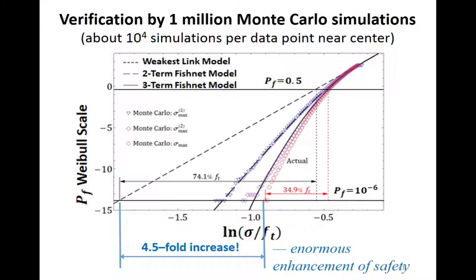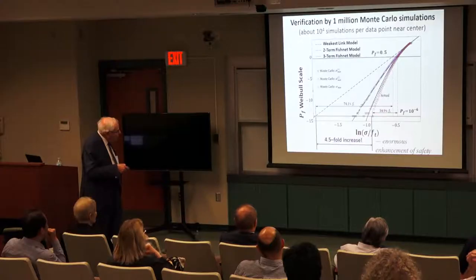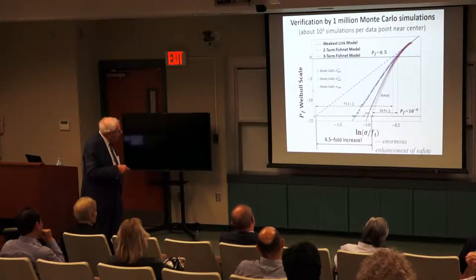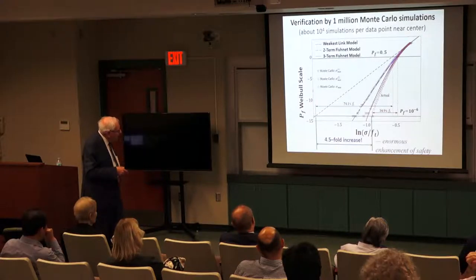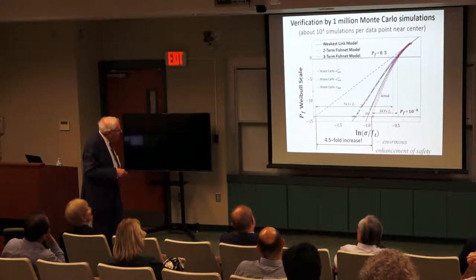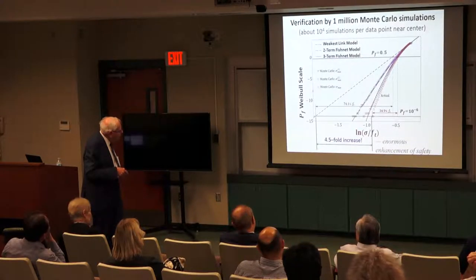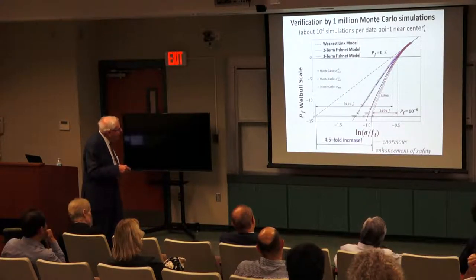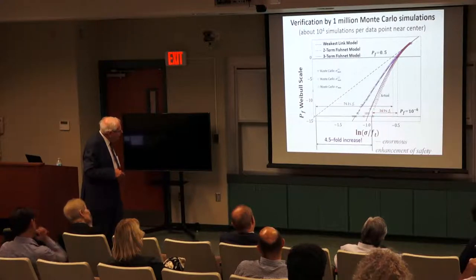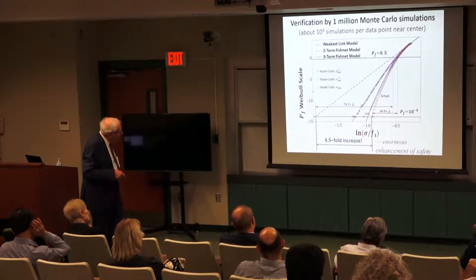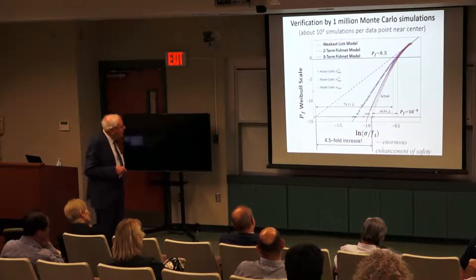This is again the line of 10⁻⁶, and you see the enormous saving. So if you compare to weakest link model, okay, positive geometric structure failing because of one element, you get this. If we can induce the fishnet action, it means this alternating series parallel, you get from 74% to 35% away in terms of safety. It's a 4.5-fold increase, enormous enhancement of safety.